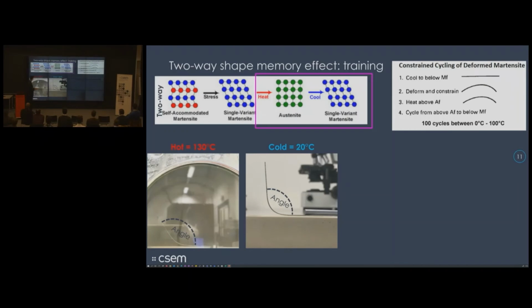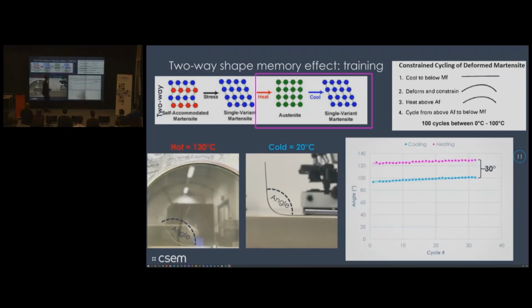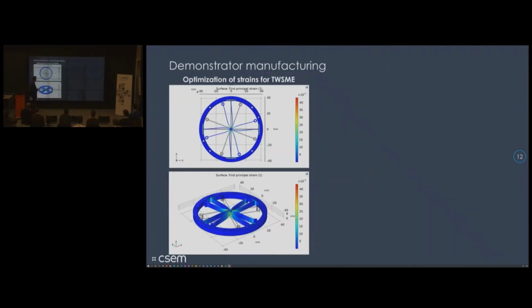flexure blade, and we have observed two-way shape memory effect. So in the hot state at 130 degrees, it was having a higher angle, and in cold state at 20 degrees, it was having a different angle, and we were measuring. There was roughly 30 degrees of difference between hot and cold state in 0.6 millimeter thick blade. There is a slight shift or creep of these angles. This is something that is observed also in conventional shape memory alloys. It's something that is related to the two-way shape memory effect, that it's difficult to obtain perfect stability, and either it can be considered in the design, or there are some very few tricks that can be worked with.